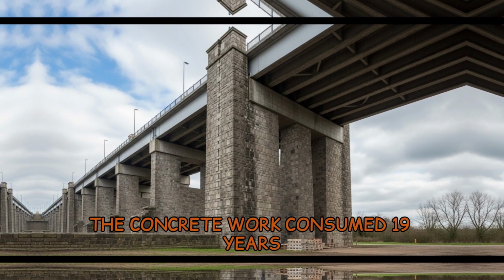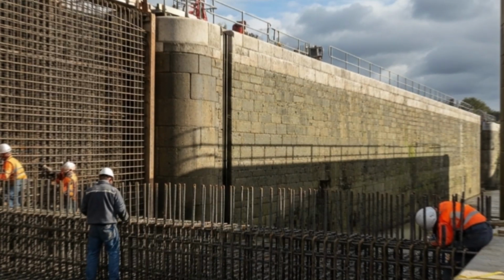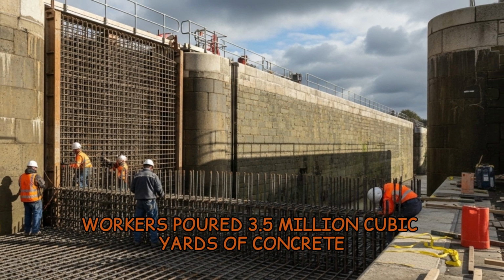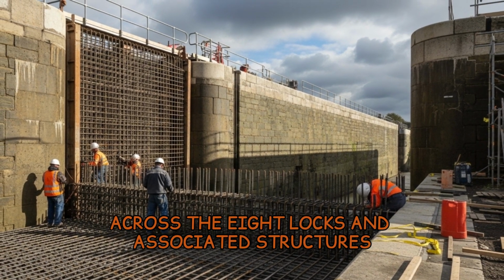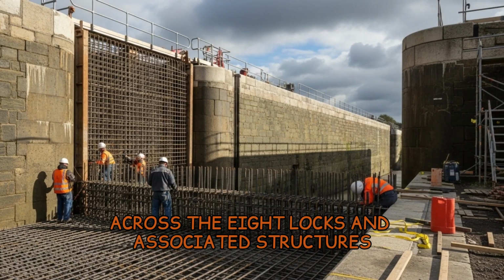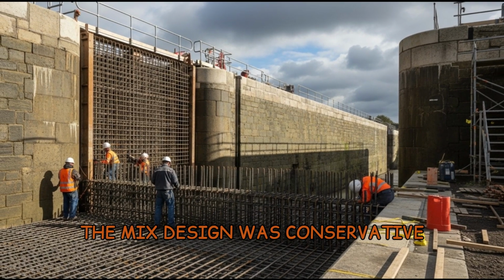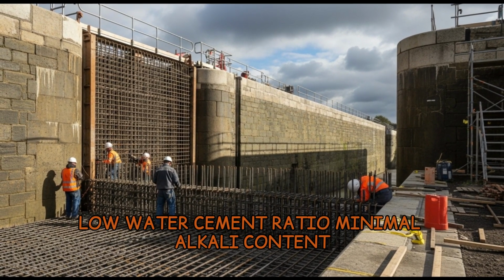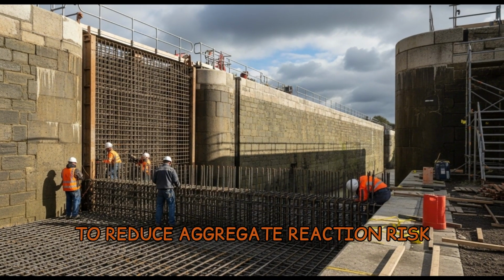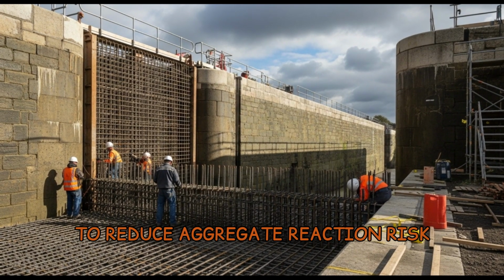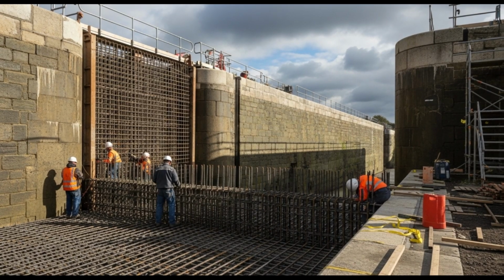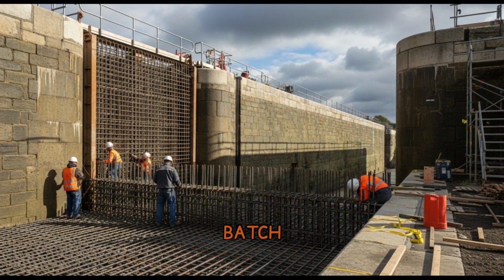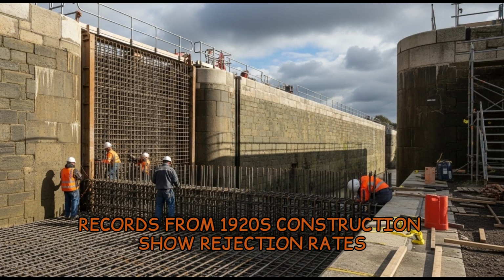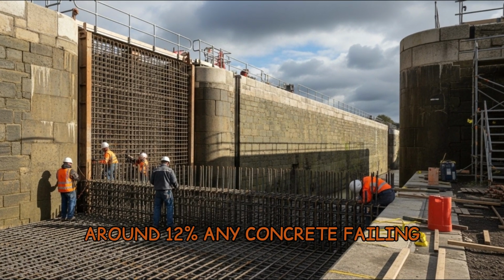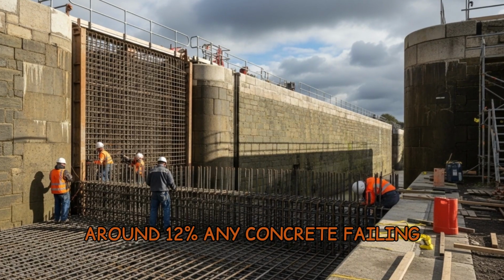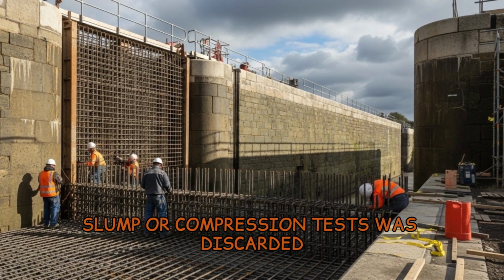The concrete work consumed 19 years. Workers poured 3.5 million cubic yards of concrete across the 8 locks and associated structures. The mix design was conservative. Low water-cement ratio, minimal alkali content to reduce aggregate reaction risk, and extended curing periods. Quality control was rigorous. Batch records from 1920s construction show rejection rates around 12%. Any concrete failing slump or compression tests was discarded.